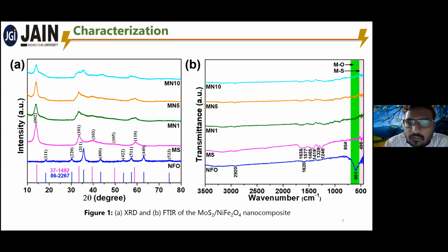in the cubic phase. In FTIR, we can see that in nickel ferrite the peak around 600 represents the metal-oxygen bonding, while in MoS2 the peak around 500 represents the molybdenum-sulfide bonding. Other than these two important peaks, several other peaks are observed in MoS2, for example around 1300, 1400, and 1500, which come from the thiourea added during our synthesis procedure, representing C-N stretching or N-C-N stretching, or NH2 group deformation.